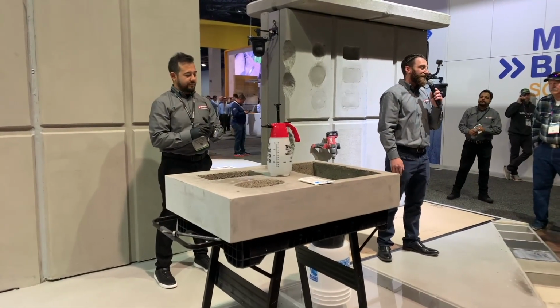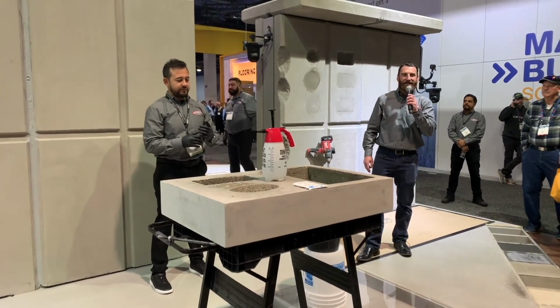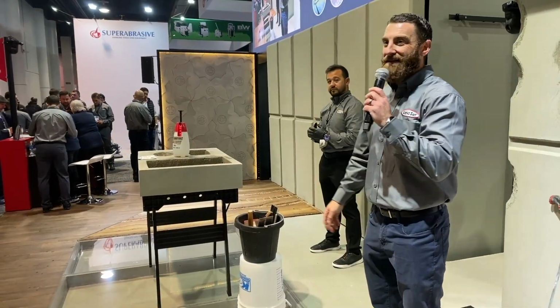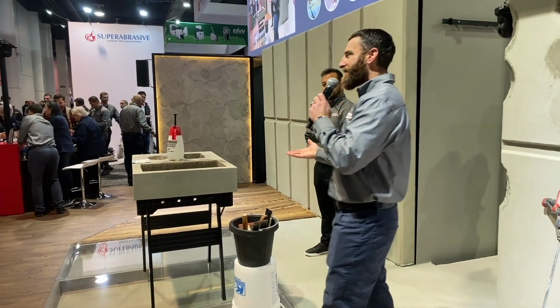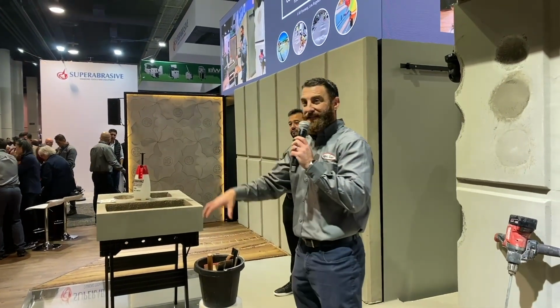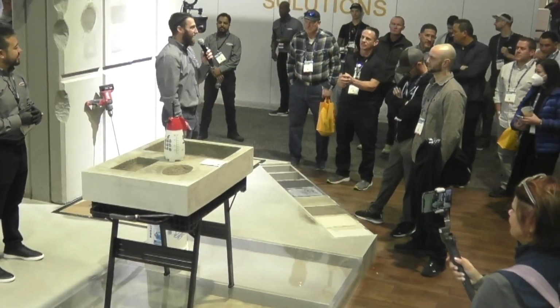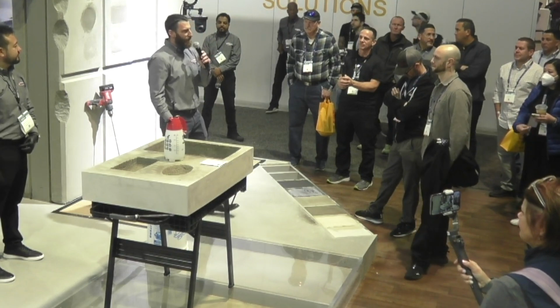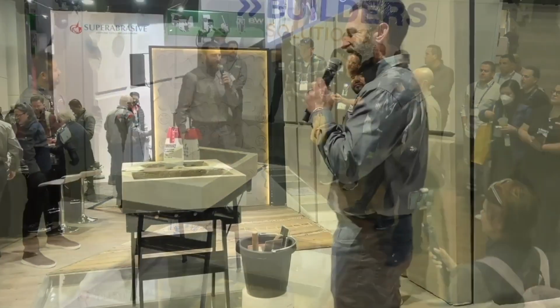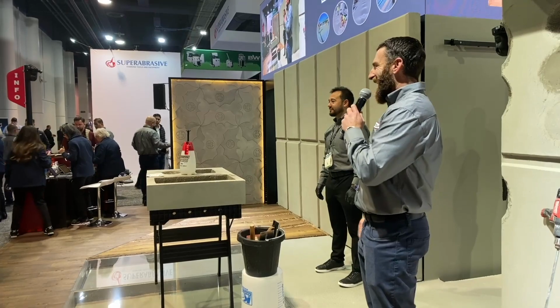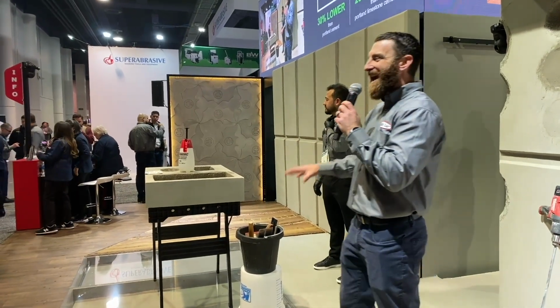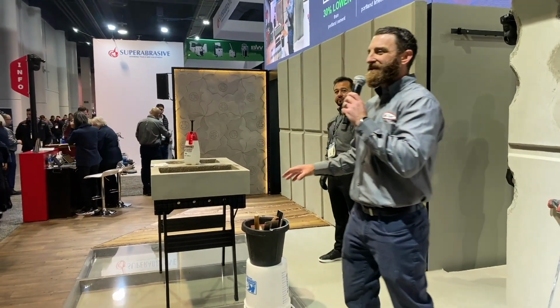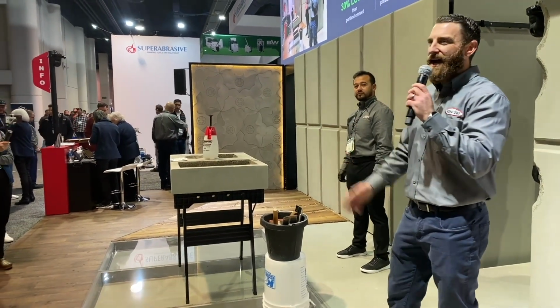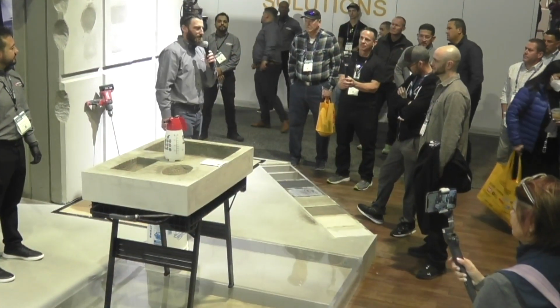We have some brand new durability data out of the I-10 freeway in Los Angeles. Back in 1998, Caltrans installed 2 lane miles over just a 55-hour closure window. Fast forward 25 years later, and Caltrans allowed us to come back out and sample that in-place concrete. So thank you to Caltrans for allowing us to get back out there and closing those lanes, and also for handling all the angry phone calls and emails because of the extra traffic that created in Los Angeles. Anyway, what we found is that concrete had 11,000 PSI after 25 years, and the flexural strength was almost 3 times what it was measured at back in 1998.